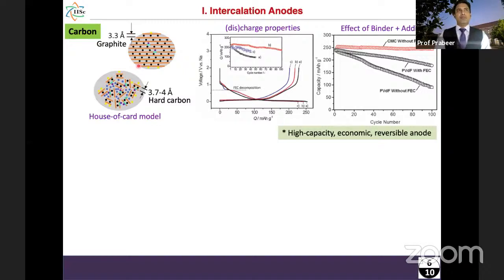But when we make hard carbon, which you can think of as a disordered graphite with some broken planes, and some localized graphitic domains, then it can lead to something called the house of card model. And here the interplanar distance we can increase to 3.7 to 4 angstrom. As a result, sodium can easily penetrate. This hard carbon has been shown to really intercalate and deintercalate sodium very nicely. As a result, we can get capacity around 220 milliampere-hour per gram.